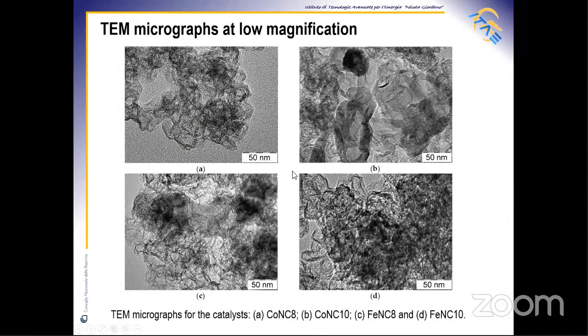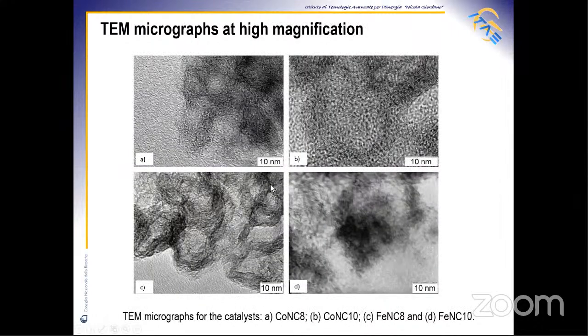For the TEM analysis, there are portions of space visible at low magnification in which the particles are more agglomerated. As expected, the higher the temperature, the larger the agglomeration. Among FeNC and cobalt NC catalysts, the cobalt NC8 displays the lowest average particle size due to a better distribution of cobalt in the sol gel reported in the procedure of synthesis. At high magnification, the particles are grouped in nanoclusters, characterized by a mean particle size ranging from 0.2 to 0.5 nanometers. This means they are just composed by atoms or groups of them.